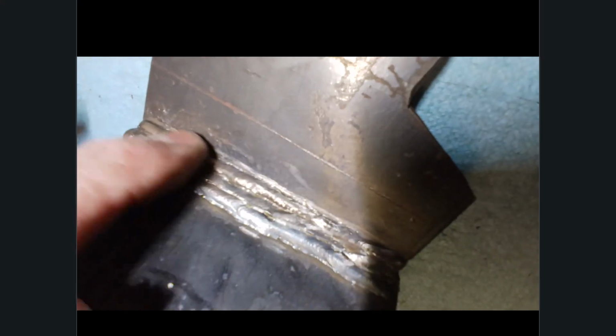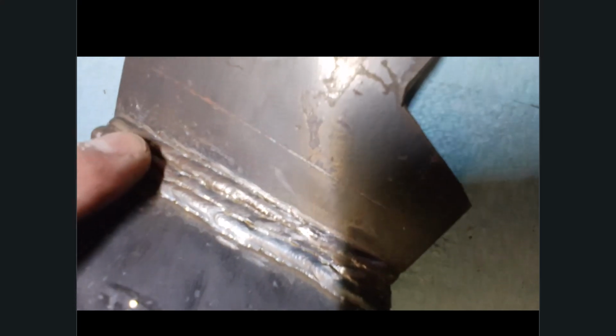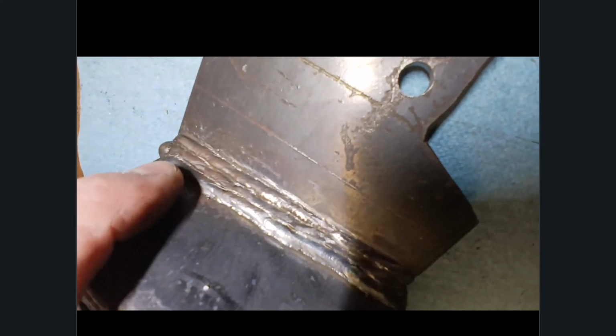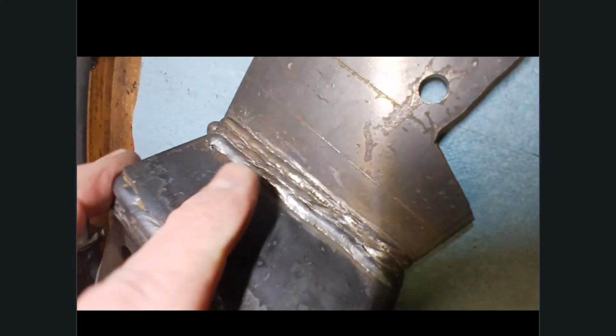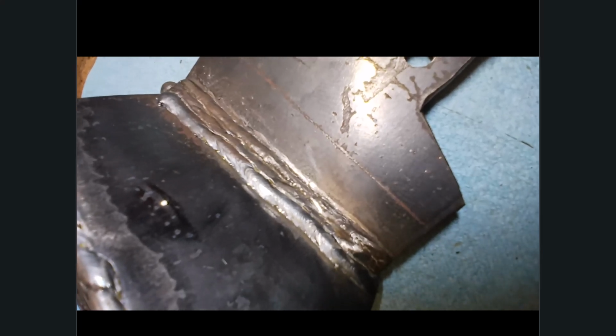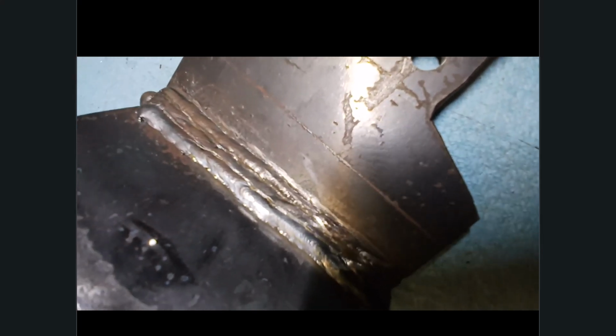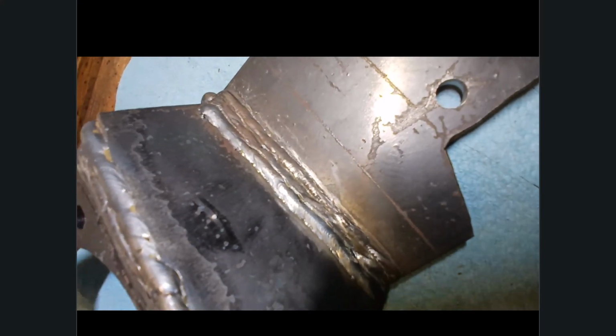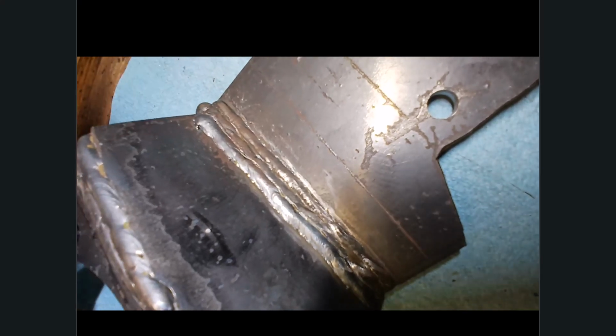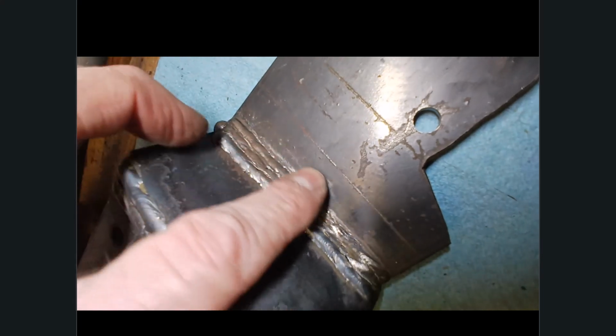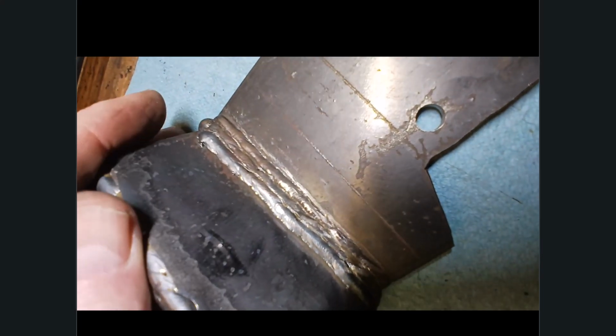I had 1/8 inch rods. You run a root pass down in the corner, and then I laid down 3 stringers next to one another over that root pass. Once you lay down your root, now you have to use arc welding. The word is with plate steel that arc welding should be used. Anything that has to support very strong structures, like construction work, building a building or building a metal frame for something that has to hold a lot of stresses and is structural steel, you should use arc welding, not MIG welding. So 7018 steel rods are the go-to for welding plate steel all day long, 7018 rods.